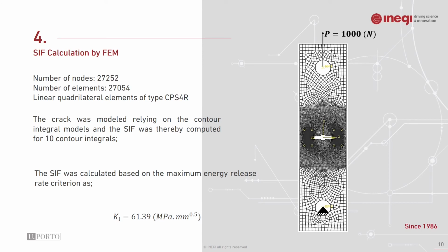The problem was numerically solved in Abaqus using finite element method formulation. On the right side, the finite element mesh is demonstrated, with the applied load, the boundary condition, the number of elements and nodes; the CPS4R elements have been used. So the crack was modeled relying on the contour integral models, and the SIF was calculated for the 10 contour integrals based on the maximum energy release rate criterion. So the mode 1 SIF was calculated as 61.39.